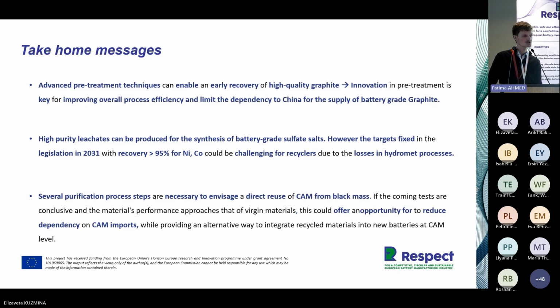Regarding the hydrometallurgical treatment, high purity leachate production is possible, and we will manage to have battery-grade sulfate salts in Europe. However, we should not underestimate the amount of losses that could be generated in the process. The results I've shown are only for 3 of the process steps, but in the battery recycling process, we have in total more than 20, 30 process steps. So we could have also some additional losses all over the value chain.